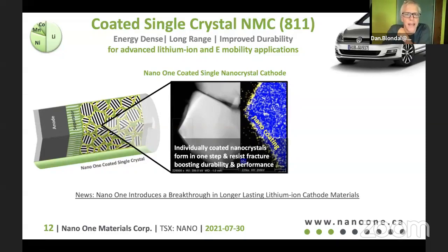So we've talked about NMC 811. NMC materials are high nickel materials. They can be 1/3 nickel. They could be 80% nickel, 90% nickel. The industry's pushing to higher and higher amounts of nickel. The problem with that is that the materials become less and less stable as you weed out the cobalt. And you have to compensate for that with other materials. And so we've developed a niobium coating that goes around the outside of the cathode materials.